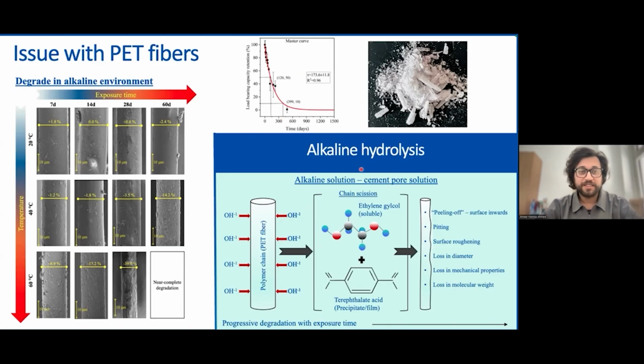And here you will see the reason causing this kind of degradation, which is basically the alkaline hydrolysis process. These PET fibers are attacked by hydroxyl ions, and that destroys the polymer structure into monomers, for instance ethylene glycol and terephthalic acid. The ethylene glycol dissolves, but the terephthalate either forms a film around the fiber, or if you continue the high alkaline exposure for longer, it starts to precipitate as small crystals.